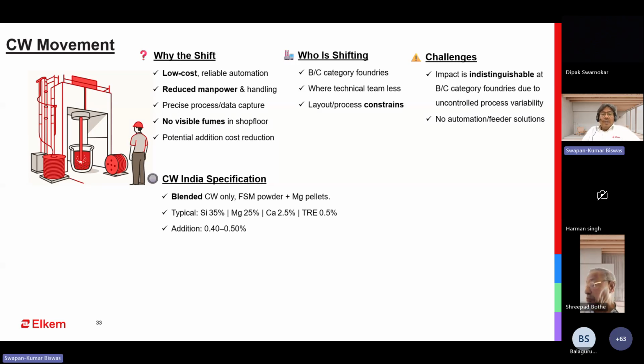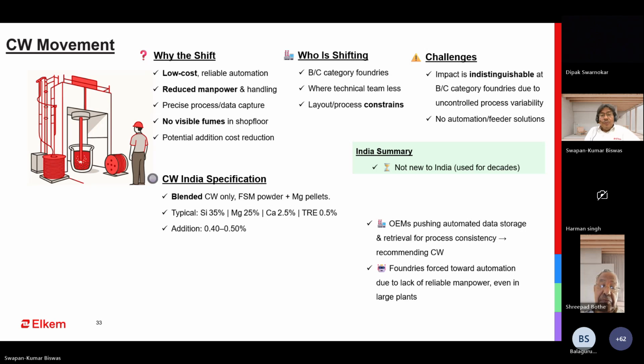And cold wire is a blend of ferrosilicon magnesium powder with pure magnesium. This is a combination. Typical composition is around magnesium 25% with calcium plus rare earth content. And the addition rate, whatever we have observed, is around 0.4 to 0.5%. Definitely it is lower than the sandwich process. Also, there is some demand from OEMs to go with this automation. So foundry people are thinking to change over from the sandwich to cold wire because there will be some automation. So this is the push on site.